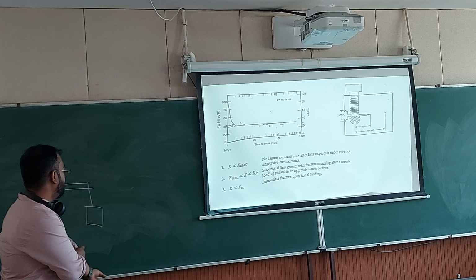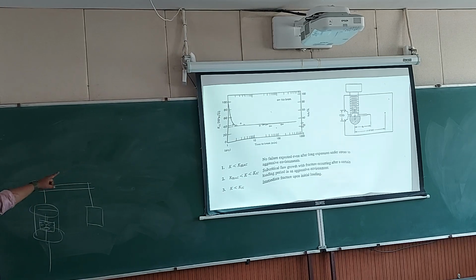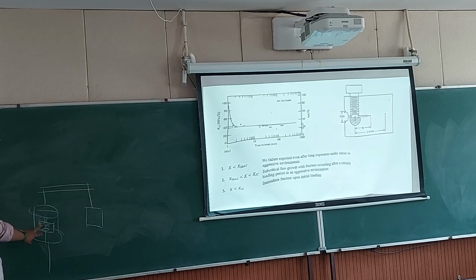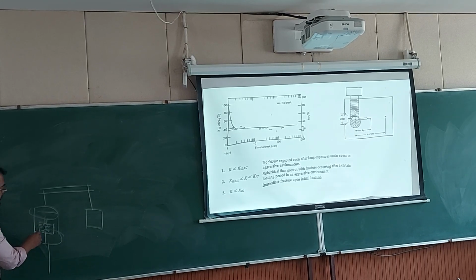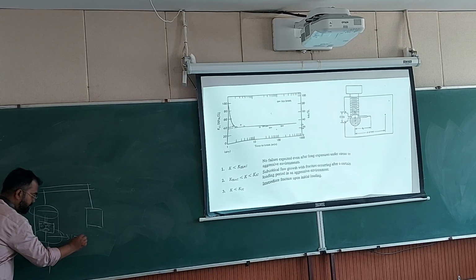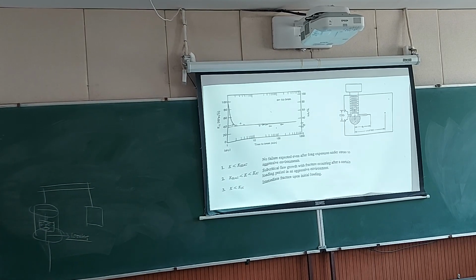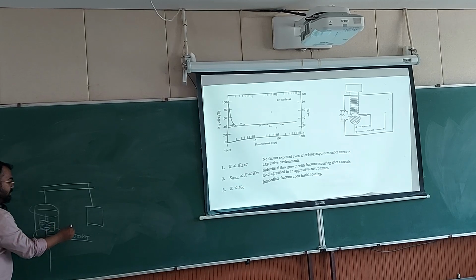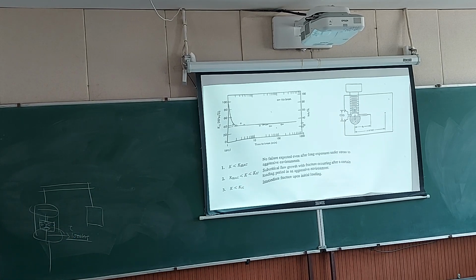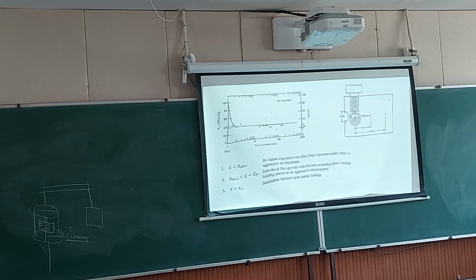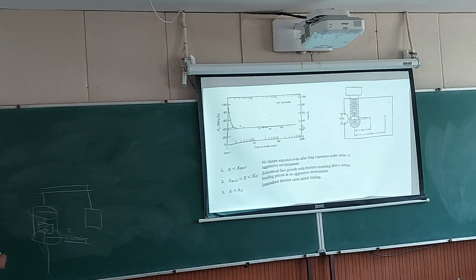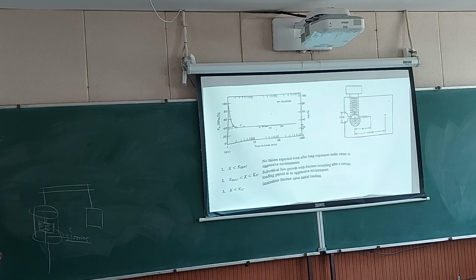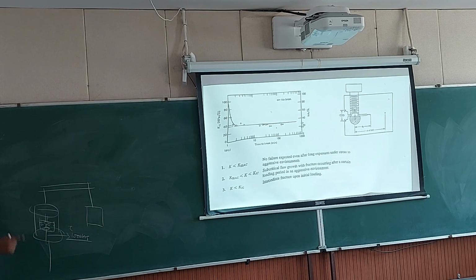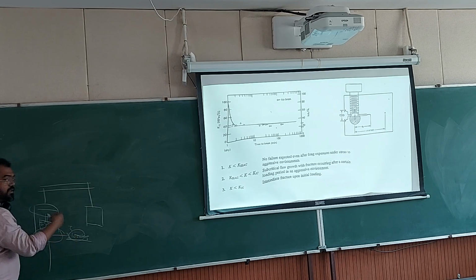Okay, so for this kind of graph, if you have to generate, you have to put a lot of samples, and you put the sample and wait for 1000 hours, or maybe less, 10 hours or whatever is the time t. You wait for time t, and then you see that it is not breaking. Okay, then you leave it there. So you just wait for this to break. Whenever this breaks, you put that point there. Then you keep on doing a lot of testing, and it will have a lot of scatter. Okay, the same material will break at 1000 hours and will also not break at 1000 hours, right?